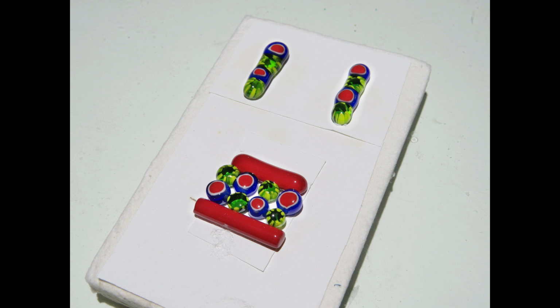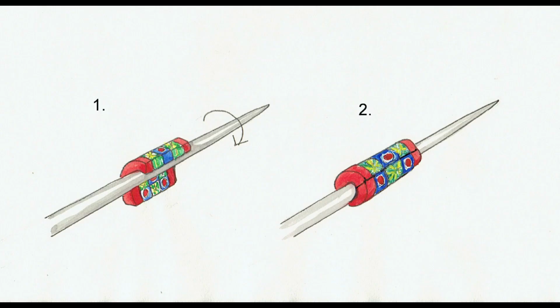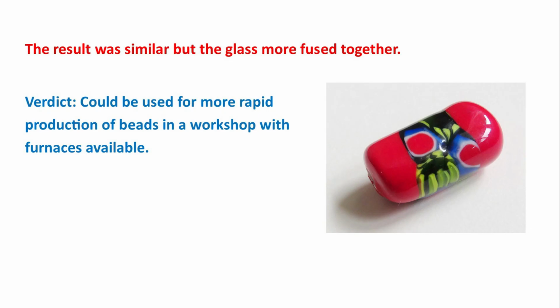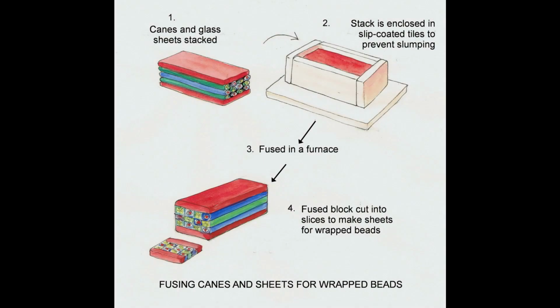Wrapped beads. This technique can be divided into two. In the first method, cane slices are arranged on a slip-coated surface and fused in a kiln into small sheets. Rods of contrasting glass for end caps can be laid in place at either end. The resulting sheets are wrapped round a mandrel and heated into beads. The result of this was similar to the first technique, but the glass was more fused together. Verdict: could be used for more rapid production of beads in a workshop with furnaces available.